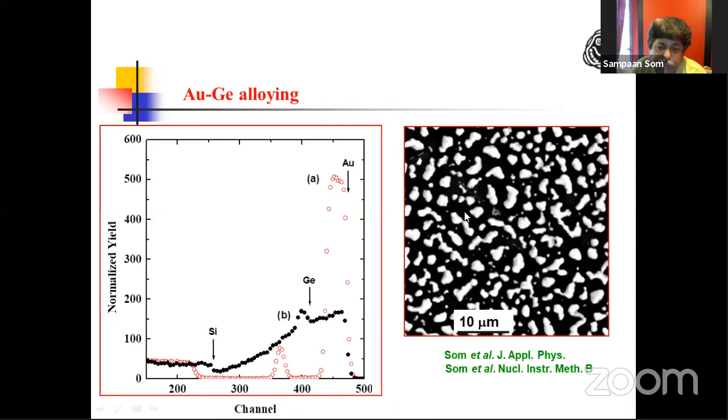So that's why silicon is appearing at its normal position. That means helium ions are able to see silicon atoms directly. They are seeing gold and germanium atoms also directly without traversing any depth. That means the surface atoms are having all three, gold and germanium in terms of these islands of gold-germanide system, and the silicon atoms are appearing through the substrate, because the substrate is getting directly exposed, because now the continuous film is transformed into several small islands. Okay, next slide please.